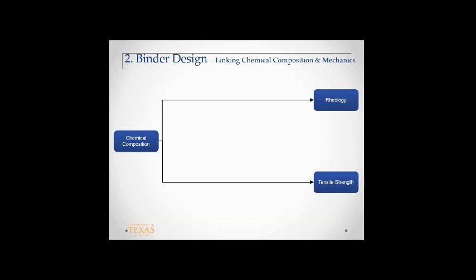And chemical composition is changing all the time because, even for the same grade, you're dealing with different producers who are getting crude oil from different sources, blending those crude stocks. Then you have people who are adding polymers, plastomers, elastomers after the binder production. Then you have people who are adding other things like liquid anti-strip agent at the construction site, or maybe a warm mix additive, people who are adding recycled rejuvenators, recycled asphalt, and all kinds of other things. So all the time you're changing the chemistry, right? So this is what is on the production side. The binder producer, the contractor, the construction, they are all messing with the chemistry of the asphalt binder.